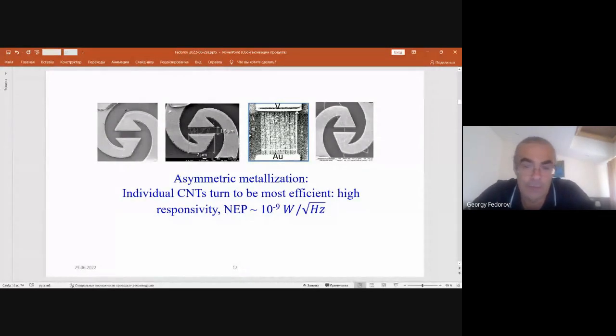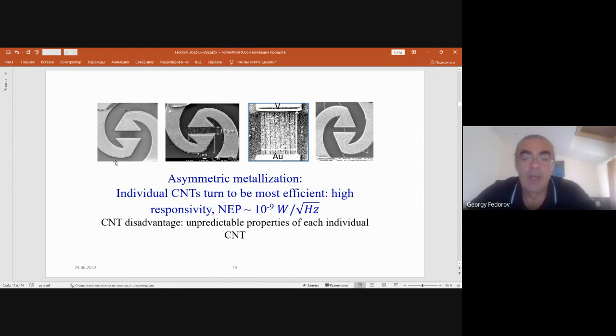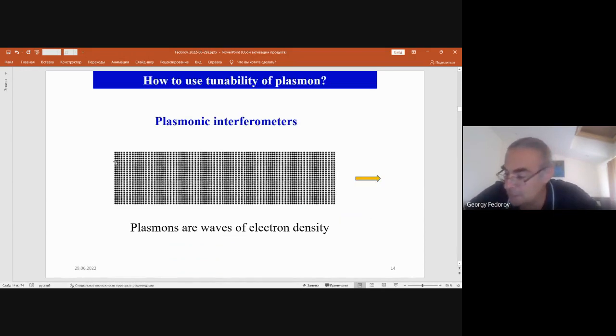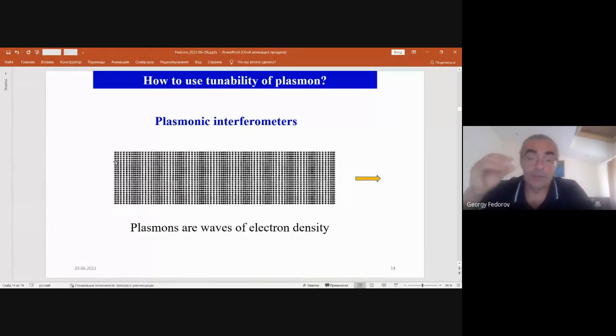properly understood, and it's different for individual nanotubes, graphene patterns, and graphene, which you can call continuous graphene. So I'm not talking about this too much. One important thing here is that we noticed some features of plasmonic response in the case of CVD graphene and continued to go along this way. And this is the main part of my talk, which is devoted to the results we obtained by concentrating on what happens with plasmons in graphene.